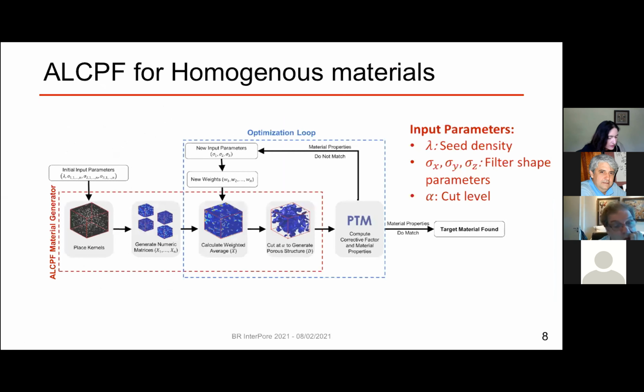Now, what I just showed was a homogeneous material. There is no gradient, no change of property in any particular dimension. And what you see here are a set of very simple input parameters. Lambda is the seed density, when we create that empty box and we throw in a bunch of seeds. The second set of parameters is the shape parameters of those inclusions. So sigma x, y, and z allow you to control the size and the shape of those inclusions. And alpha is the cut level at which we cut those little mountains that we generate by putting the seeds in there.